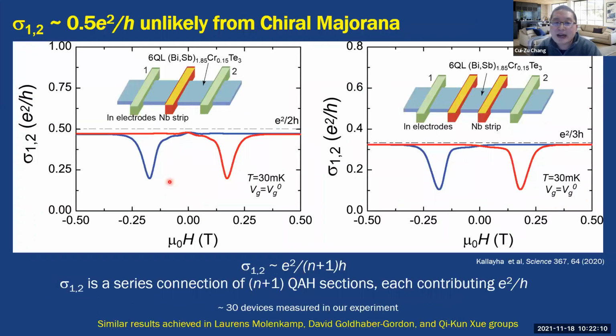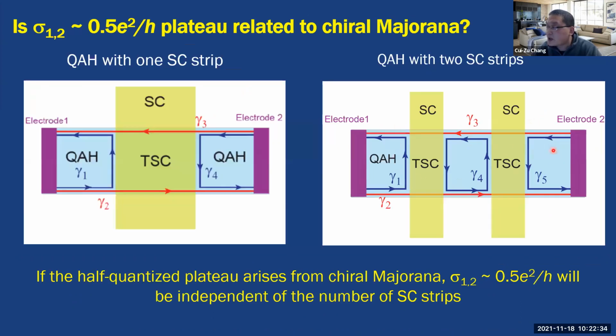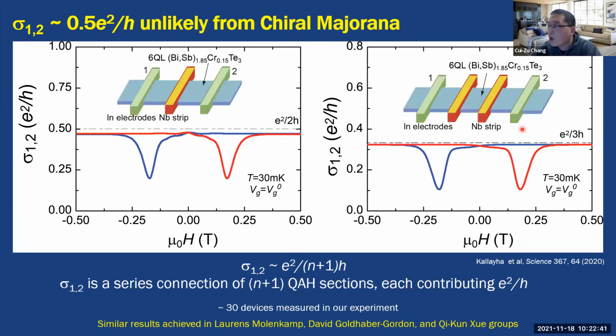So we did this measurement. Here are the transport results. When one strip is put here, the 2-terminal resistance is e squared over 2h. When 2 Nb strips are here, we can see that the 2-terminal resistance becomes e squared over 3h rather than e squared over 2h. As I just introduced, if this 2-terminal resistance were related to Majorana physics, it should be constantly e squared over 2h. But in our experiment, it becomes e squared over 3h.